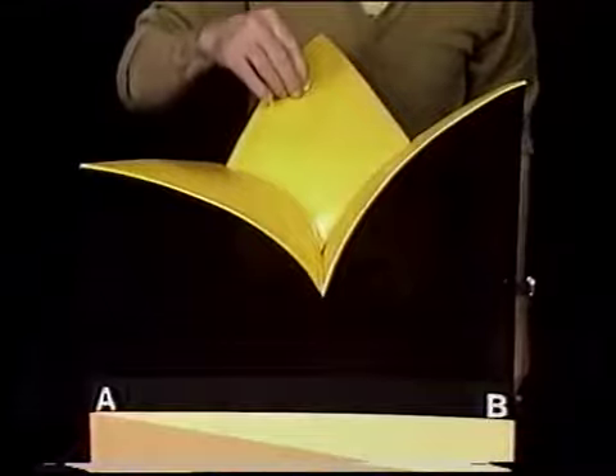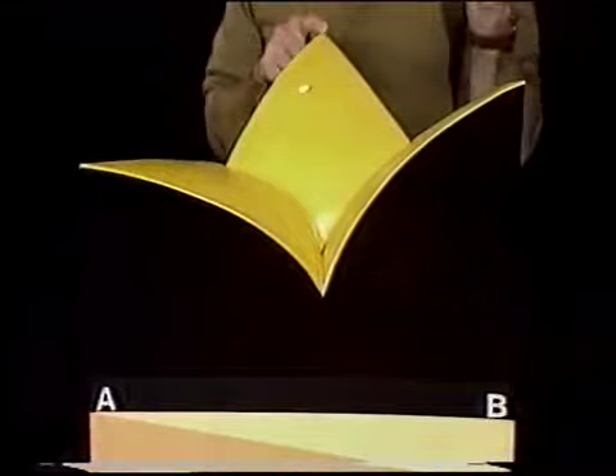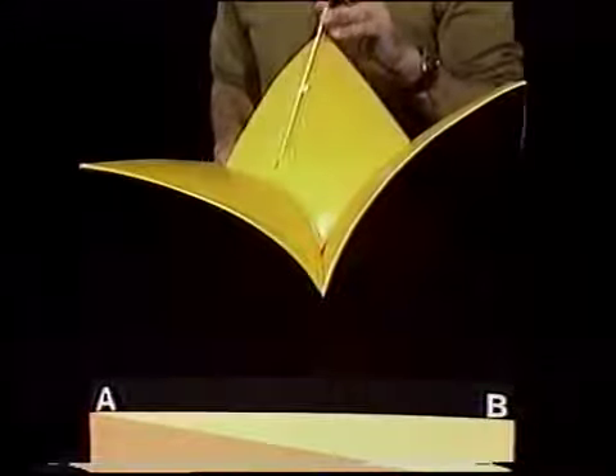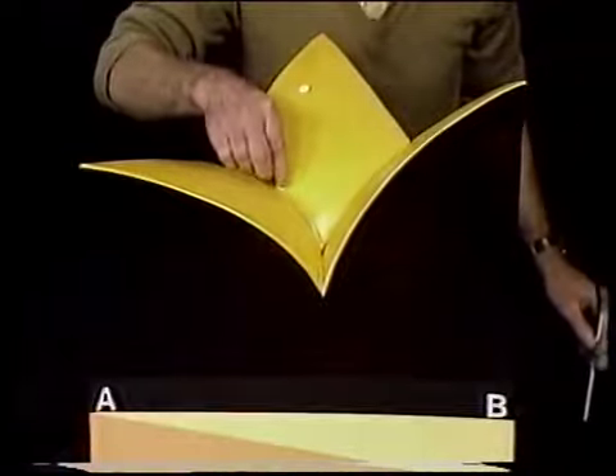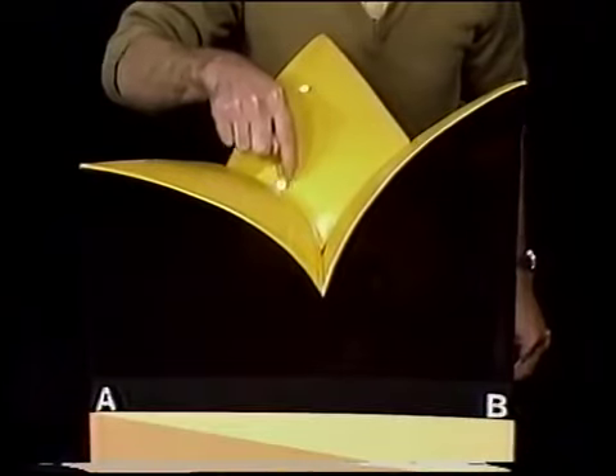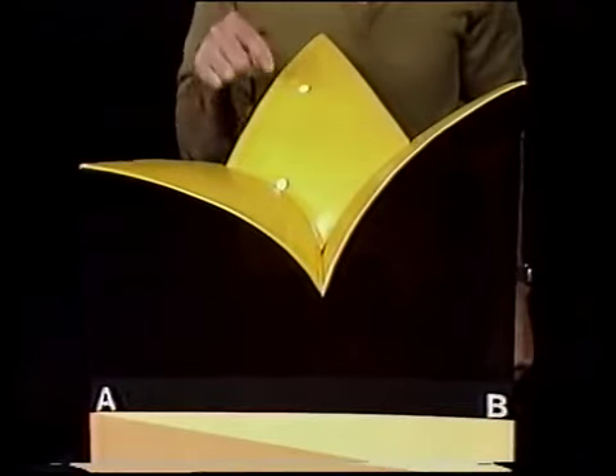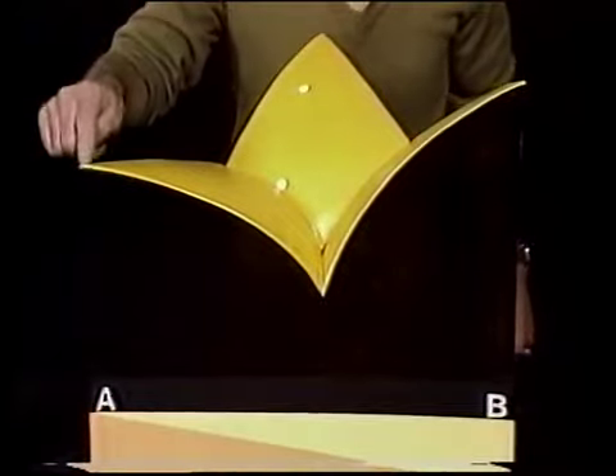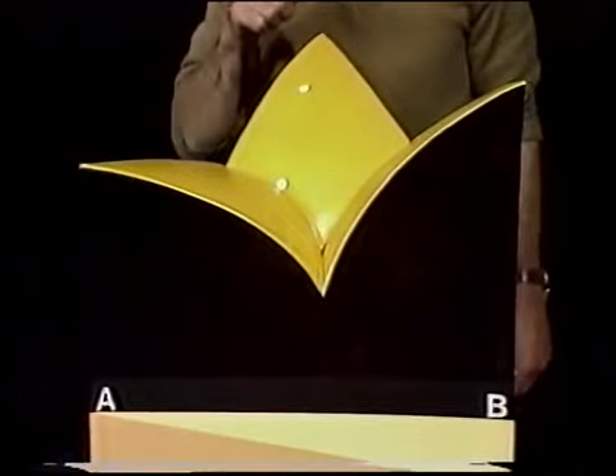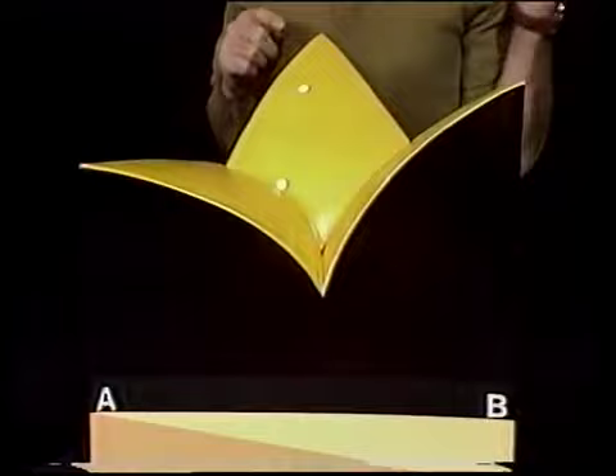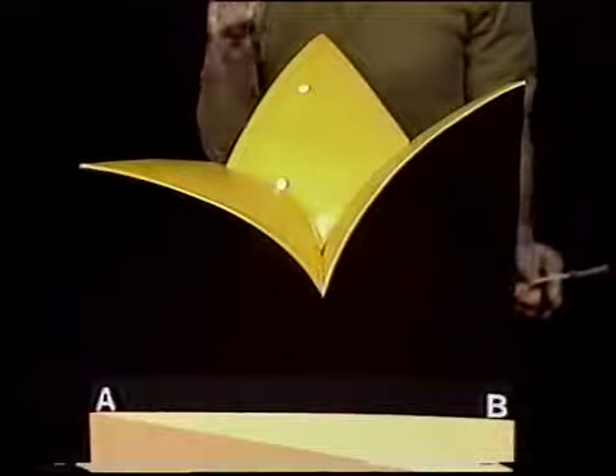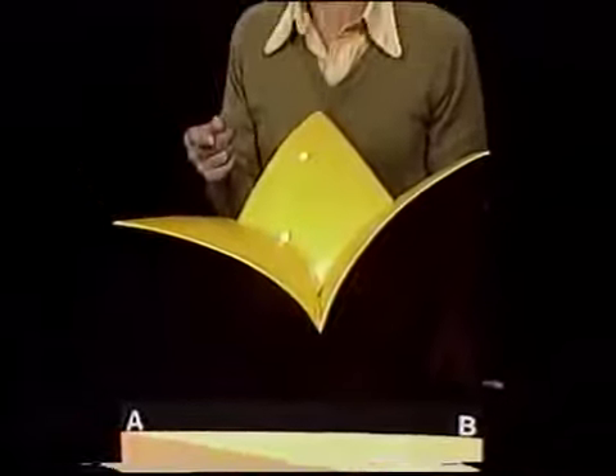If I now cool a melt that's rich in, say, C, when it intersects the liquidus, crystallization of pure C is going to drive the melt away from the C corner down to the cotectic. When it reaches the cotectic, the only way the liquid can move is down the cotectic valley. It changes direction away then from both the C and the A corners, which means that pure A must be crystallizing as well as pure C. In other words, a cotectic in a ternary system is the same as a eutectic in a binary system. When a liquid reaches it, a second phase has to crystallize.